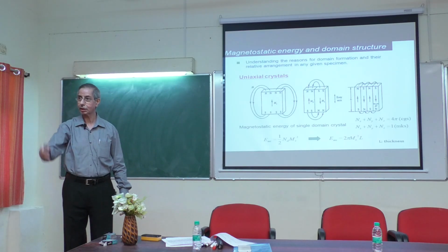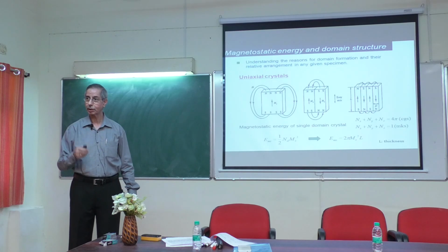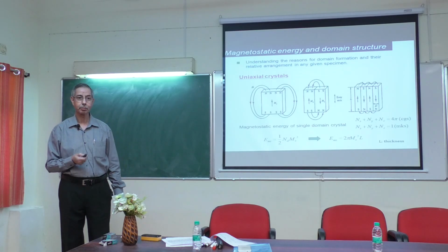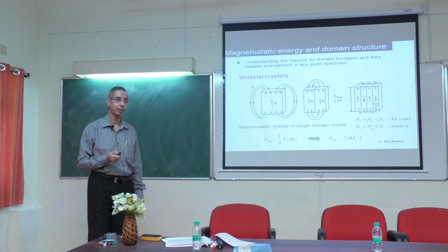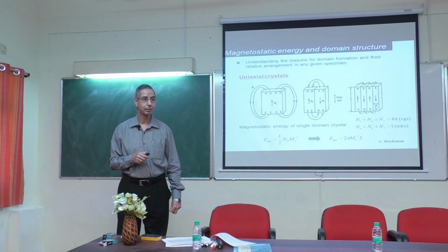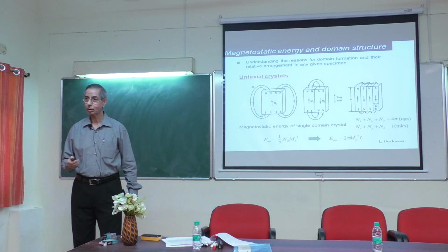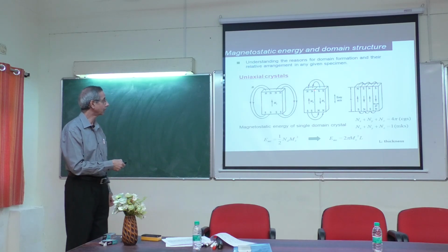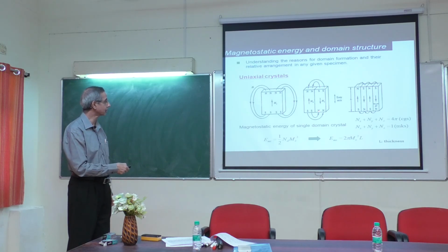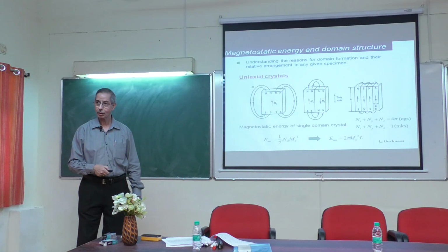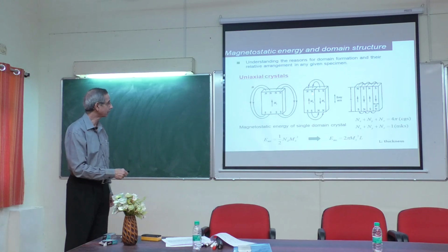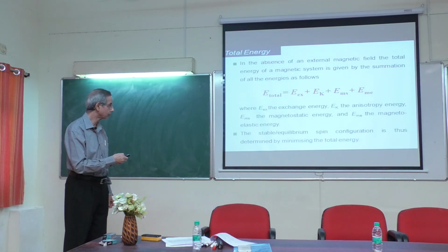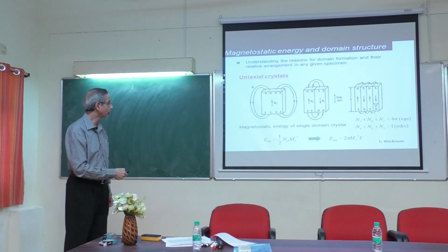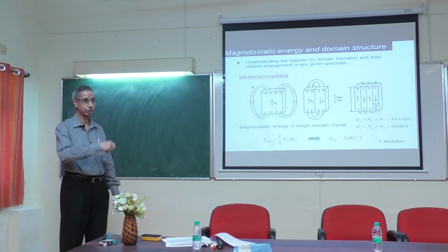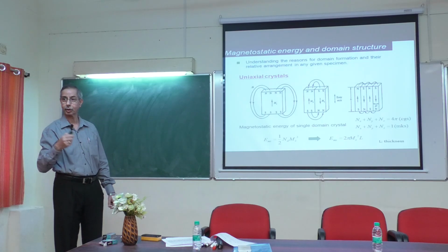So just by creating one domain wall and dividing it into two domains, the magnetostatic energy has reduced by a factor of 2 roughly. Okay? So now what will happen is that in the process, I have created this domain wall. Now in the domain wall, magnetization has to go from this orientation to this orientation. It has to go from this to this orientation.